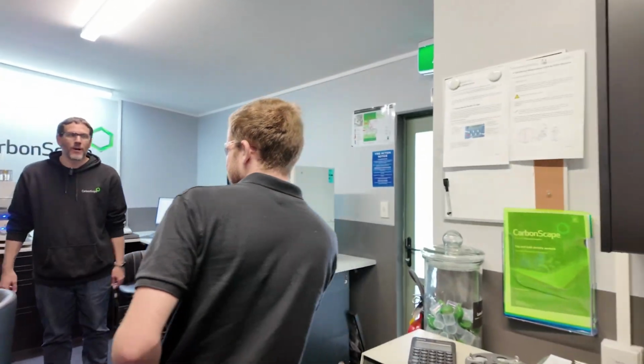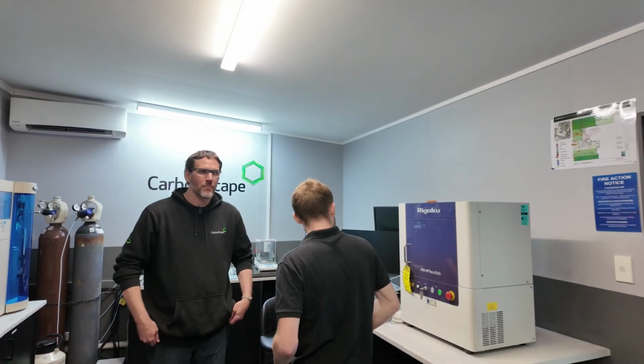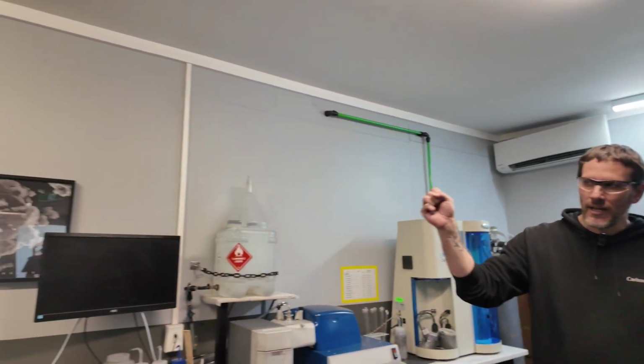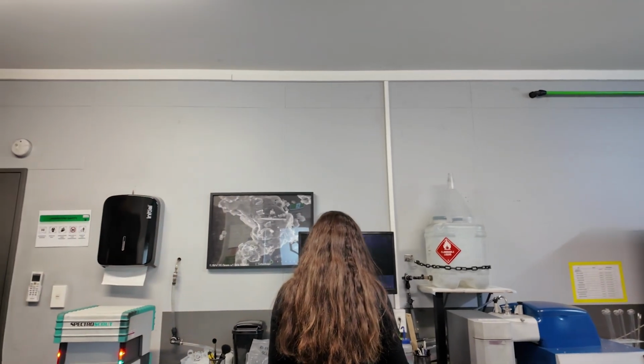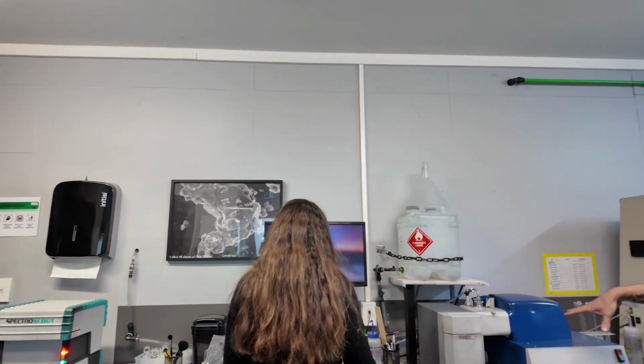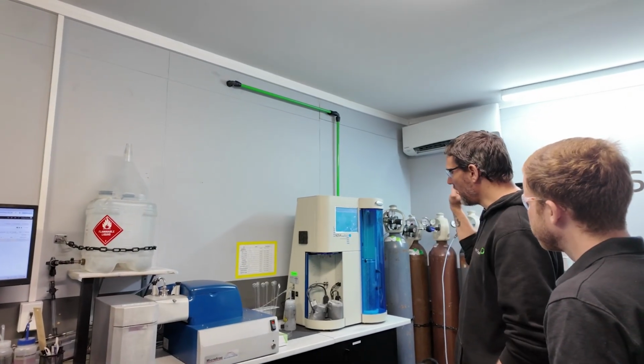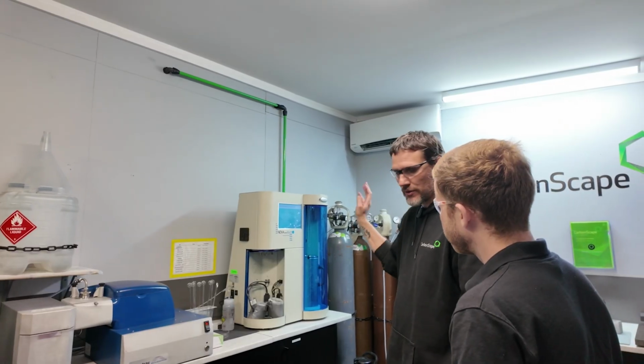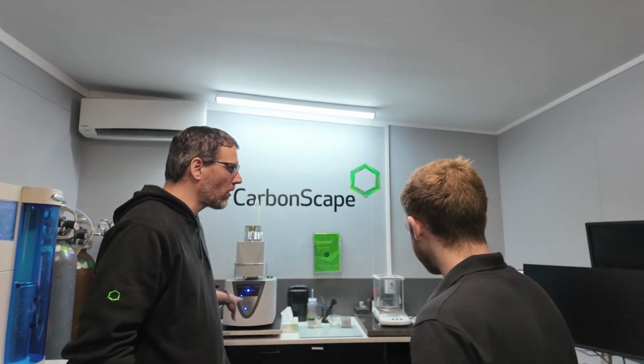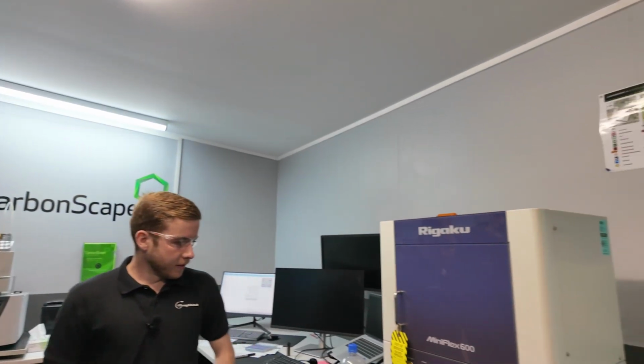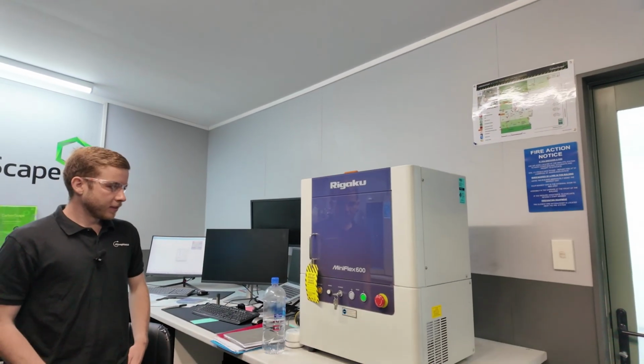This is where we do all the powder, well, not all of it, but most of the powder analytics. So we have impurity analysis using X-ray fluorescence. We have particle size analysis using laser diffraction, and we have surface area using nitrogen absorption. We have some TGA to look at the carbon content of the charcoal, and we have X-ray diffraction to look at the quality of the graphite crystals.